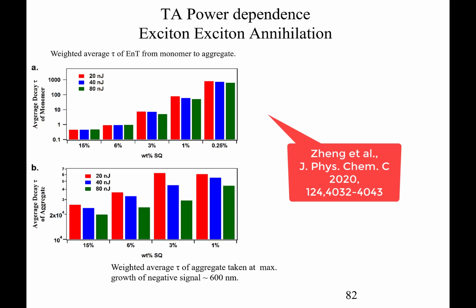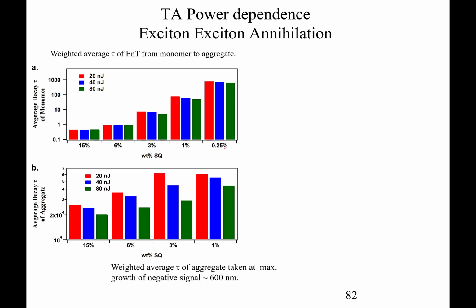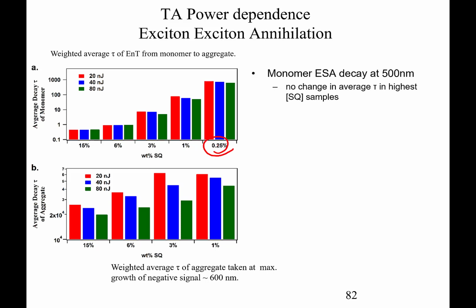So next we can think about energy transfer and how that shows up in a transient absorption power dependence experiment. The power dependence comes from exciton annihilation. And what we find is that with the low concentrations of Squaraines, there is indeed a small power dependence. What this demonstrates is that with 80 nanojoule pulses, so 4 times higher energy fluence, I guess, power increase, there are now more excitons generated, and with more excitons being generated, this is a second order rate process. Those excitons need to find each other, and once they find each other, they annihilate each other, and the excited state drops back down to the ground state.